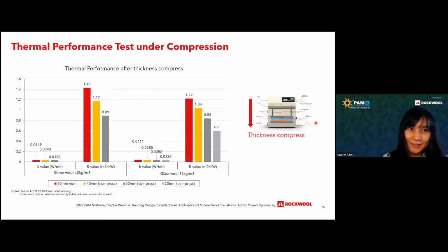Another test that we've done is because, for some roofing applications, when they do not have a spacer between the metal roof and the underneath, there will be a situation where insulation will be compressed. When you compress the insulation, thickness will be affected, R value will be compromised, U value will be compromised. So we sent the sample to an external lab, tested under ASTM C518, thermal conductivity performance at 20 degrees C mean. The same sample, we measure at nominal 50 mm, compress it to 40 mm, compress again to 30 mm, and compress again to 20 mm. We want to see what the K value is as well as the R value.